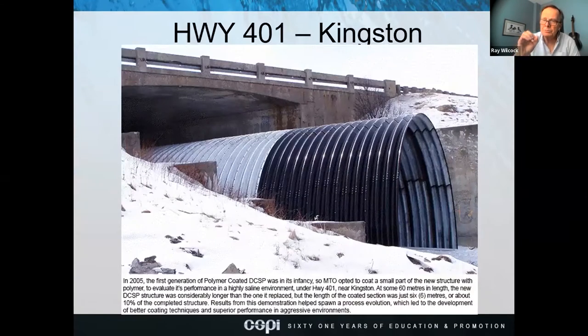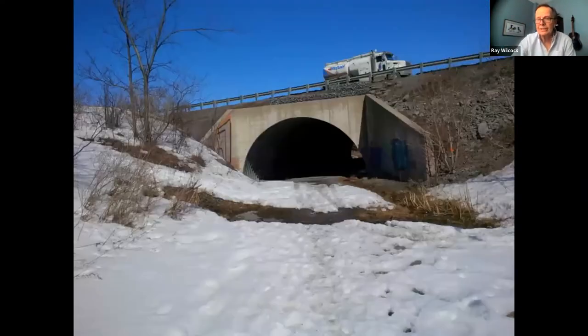This was the first polymer coated structural plate in Canada. It goes underneath the Highway 401 in Kingston at the Charbot exit. And what the MTO allowed us to do was just polymer coat the external sides of those plates. Because of the salt spray trucks that would come down the 401, they wanted to make sure that if the salt was going to be sitting on top of the structure, it would be protected down below. So these were just polymer coated at both ends of the highways, and just on the outside. There's a picture of what it looks like just a couple of years ago.